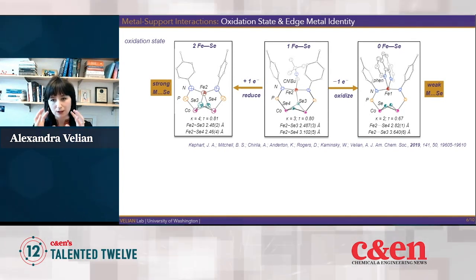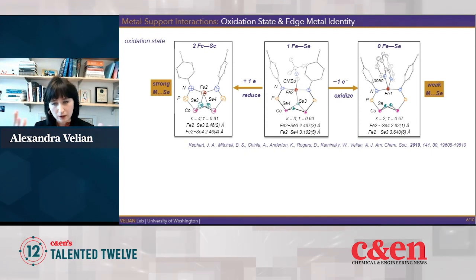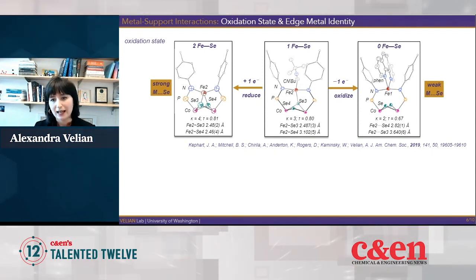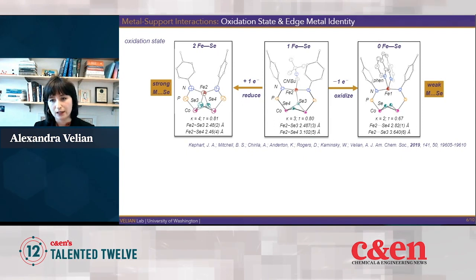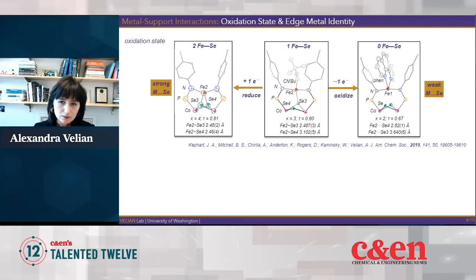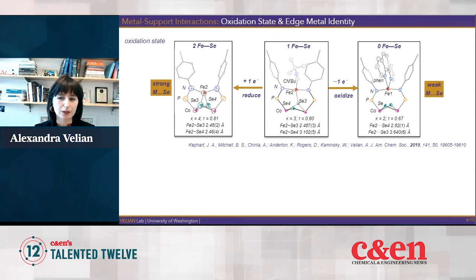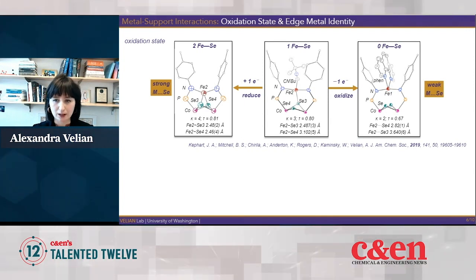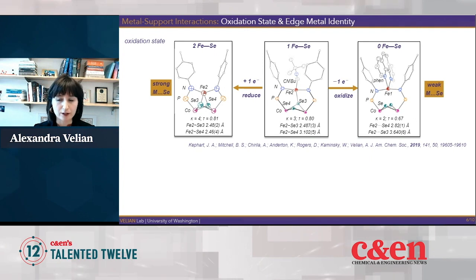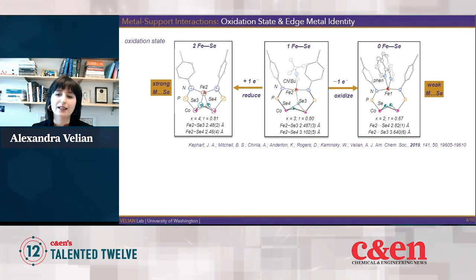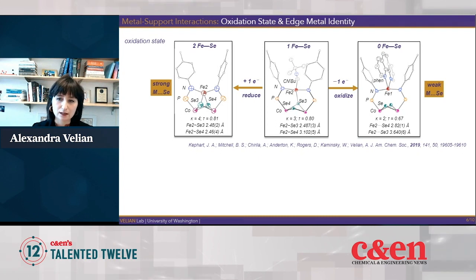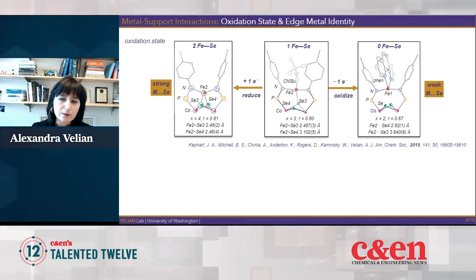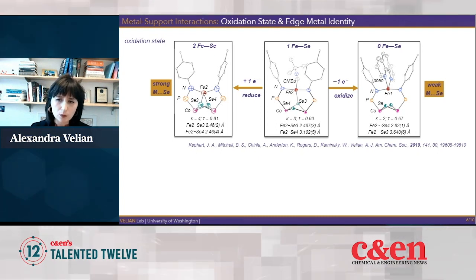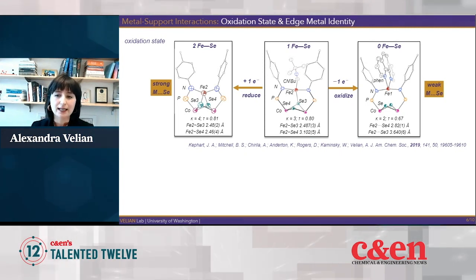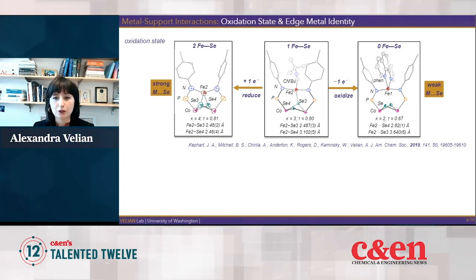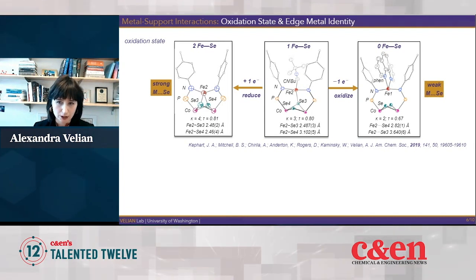And so if we highlight a single edge site on this otherwise complex cluster, I selected here the cluster that has iron on the surface, we can observe this hemilability of the edges and understand a little bit better that cooperativity. So for example, in the neutral state, a tri-iron cluster, again focusing on a single edge site using single crystal X-ray diffraction, we can see that the metal engages with an external ligand, in this case isocyanide, and a single one of the two possible seleniums exposed in this coordination pocket.